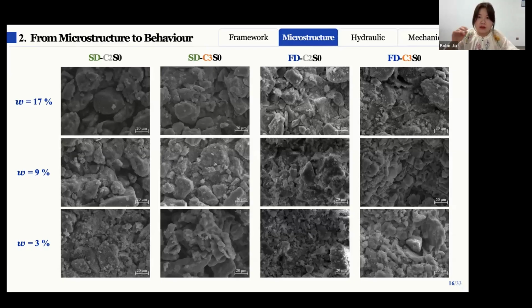And then under the faster drying, due to the rapid and pronounced upward migration of sodium chloride, the difference in salt content at the top of samples with different initial salt contents becomes less distinct at certain water contents.